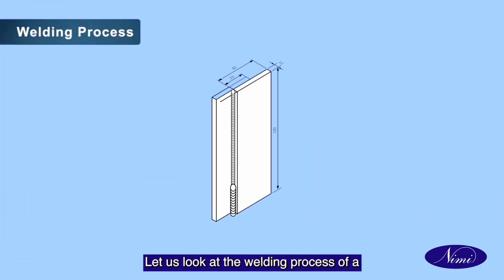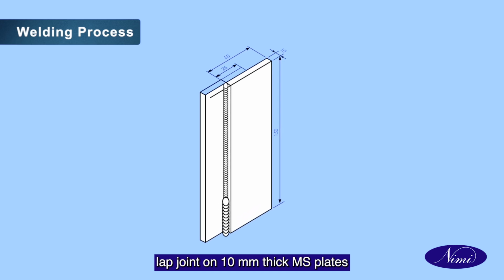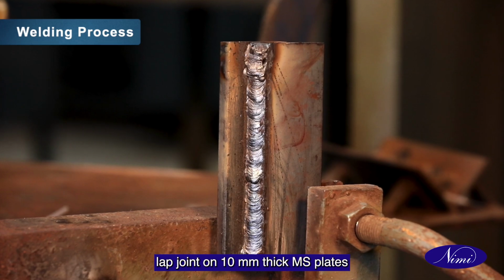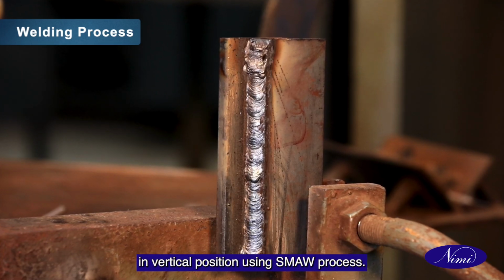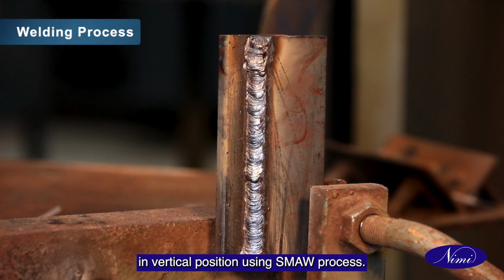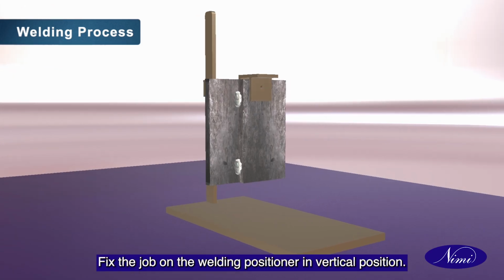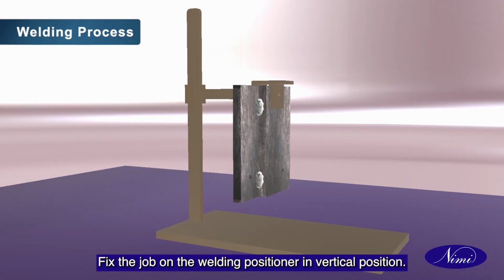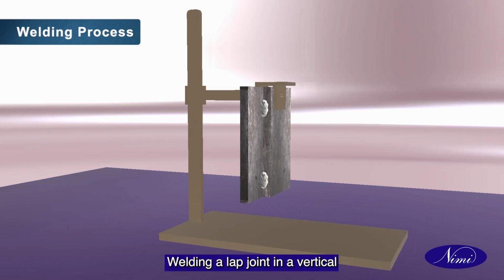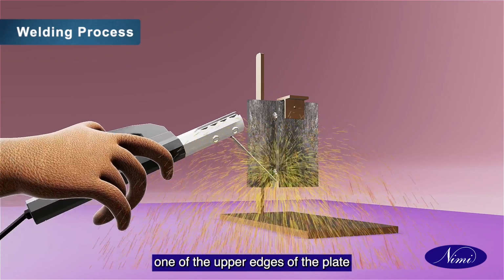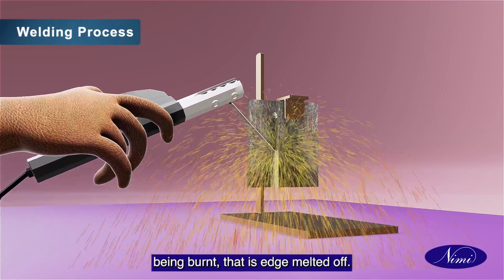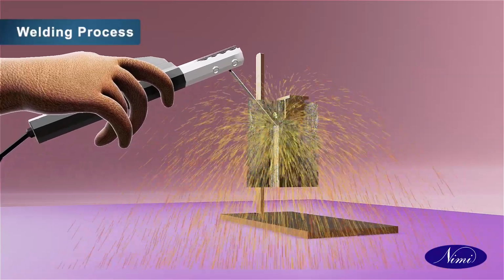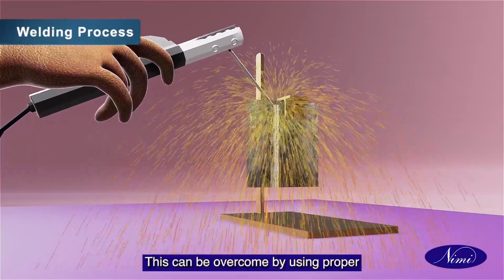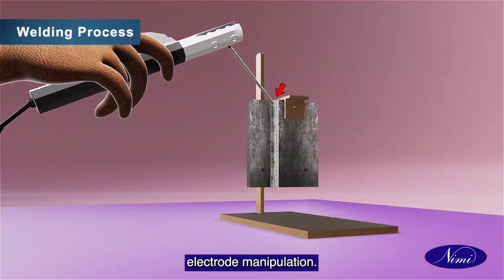Let us look at the welding process of a lap joint on 10 mm thick MS plates in vertical position using SMAW process. Fix the job on the welding positioner in vertical position. Welding a lap joint in a vertical position has always been a problem. One of the upper edges of the plate being burnt, that is, edge melted off. This can be overcome by using proper electrode manipulation.